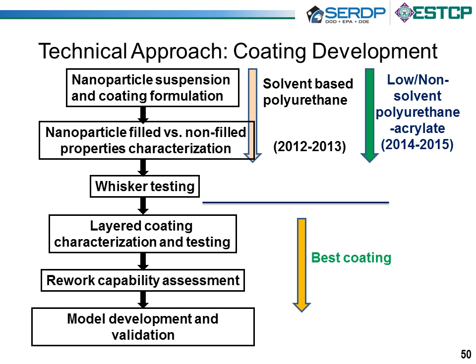So the overall technical approach that we pursue on the project is taking a look at two kinds of coating-based materials. One is a traditional solvent-based polyurethane, and the other one is actually a future greener, low or non-solvent polyurethane acrylate, which is nice because it has an ultraviolet cure and also a humidity post-cure. And we also want to take a look at layered coatings to see if some combinations of materials would provide improved whisker mitigation, while being sensitive to rework capabilities.